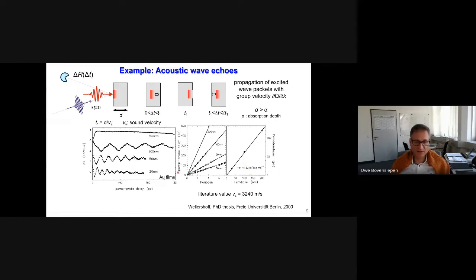observed. And you can analyze here the periods, the minima and maxima at their respective pump-probe time delays, and then plot the duration of these periods as a function of the film thickness. These are these individual data points, and then determine the velocity of this propagation from such a measurement. And if you compare the result, this work in the PhD thesis from more than 20 years ago has obtained 3,310 meters per second. This compares pretty well to the literature value of the sound velocity in gold.